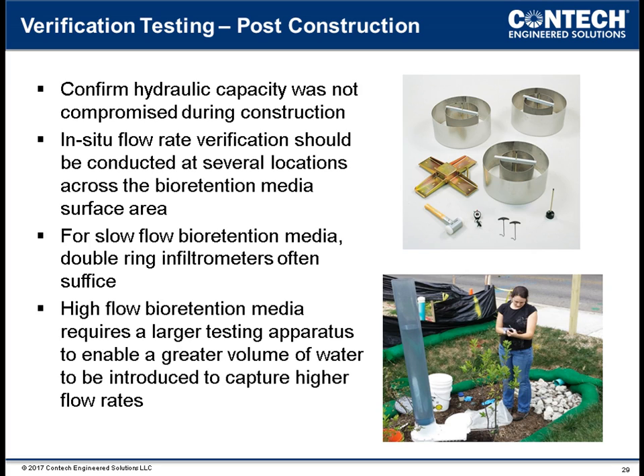Post-construction verification is highly recommended to confirm hydraulic capacity was not compromised during construction. In situ flow rate verification should be conducted at several locations across the bioretention media surface area. For slow flow bioretention media, double ring infiltrometers will often suffice. High flow bioretention media requires a larger testing apparatus to enable a greater volume of water to be introduced to capture higher flow rates. What we've essentially done is modify the lab columns for field testing, which is backed by thousands of tests.